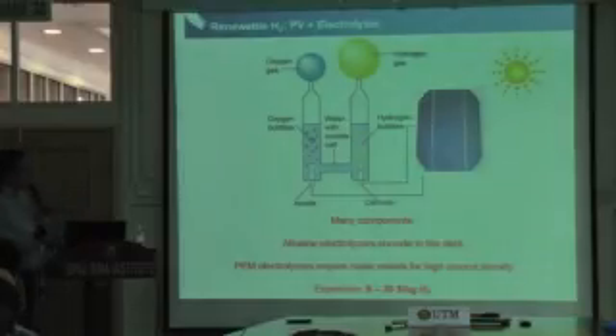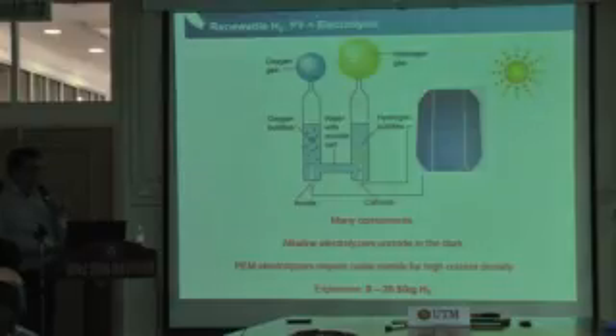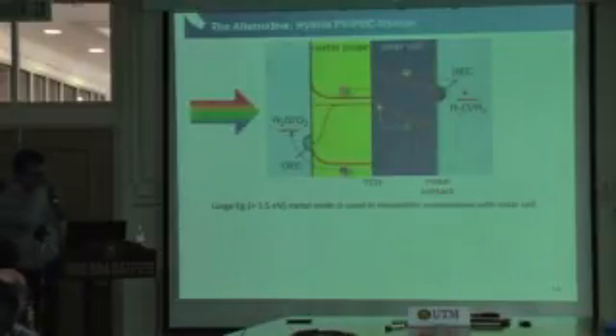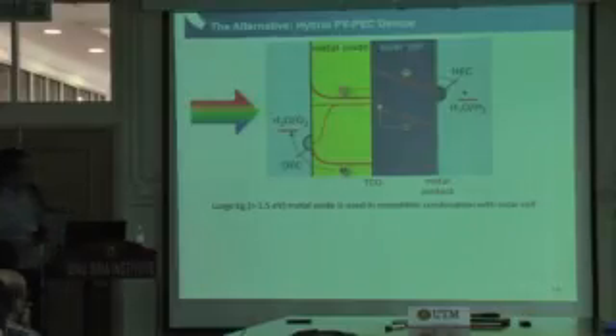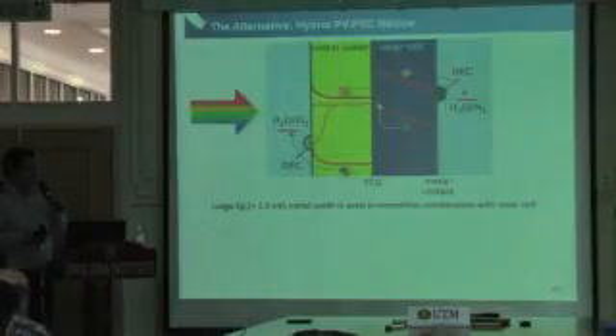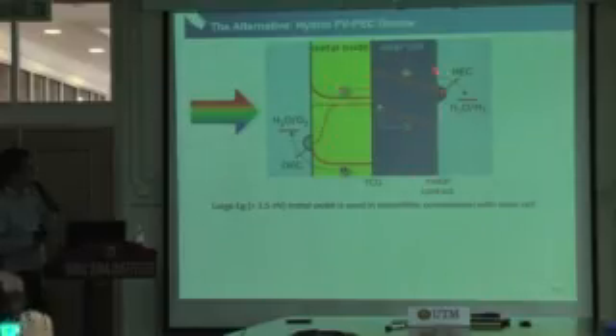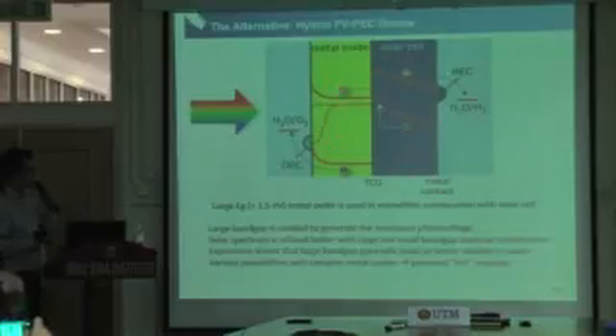So what's the alternative? It turns out that people have done the calculation, and it turns out to be too expensive. The cost of hydrogen is about $8 to $20 per kilogram, and this is definitely too expensive. So the alternative is taking advantage of a hybrid photovoltaic and photoelectrochemical device used in monolithic combination. The example over here is a large bandgap metal oxide, and we couple it with a solar cell in a monolithic configuration. Some of the advantages are shown here.